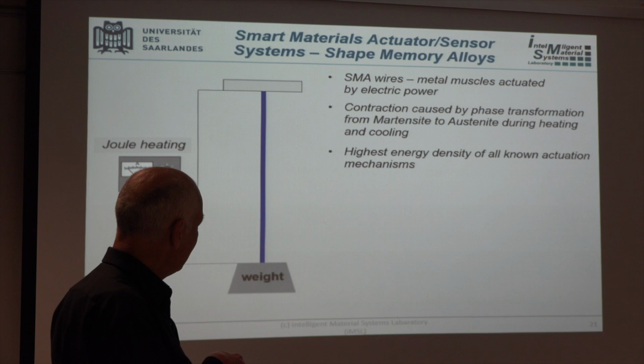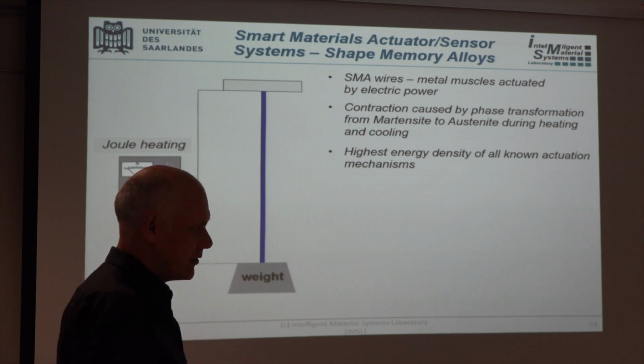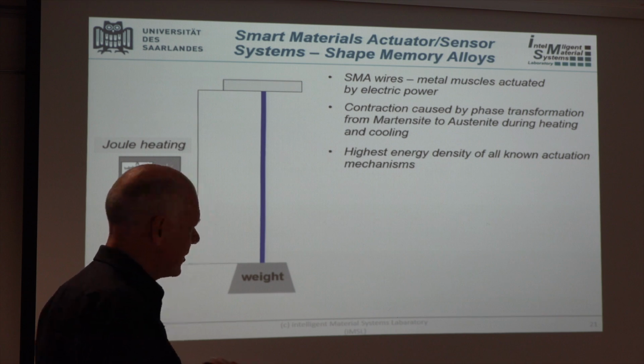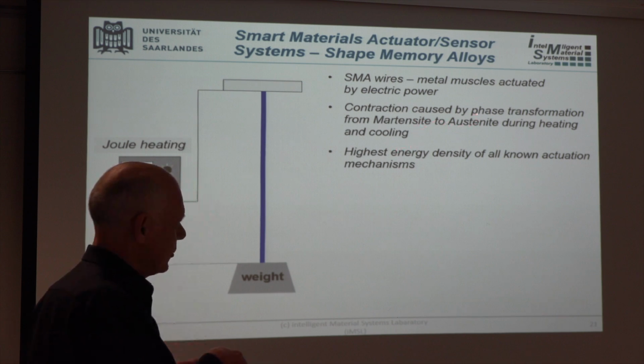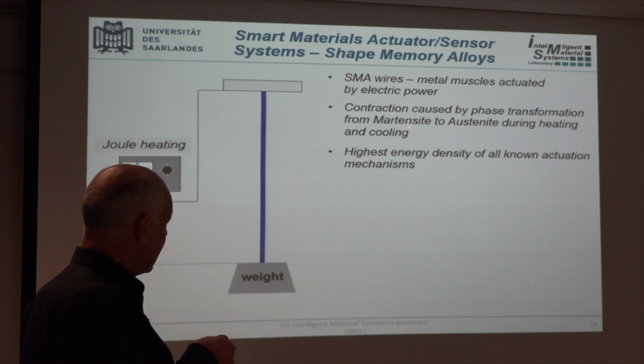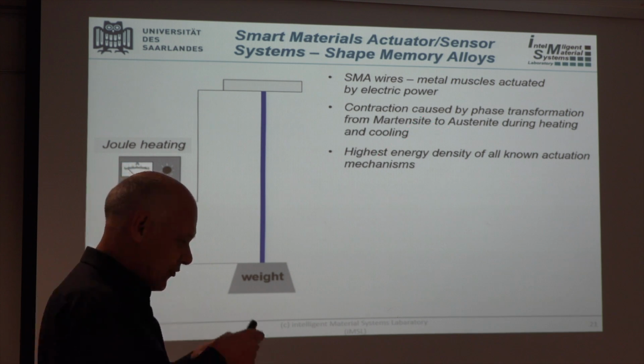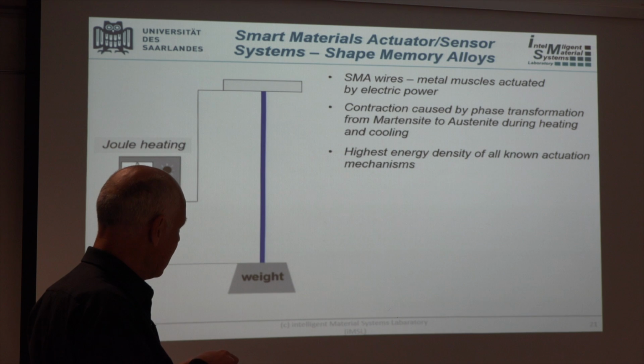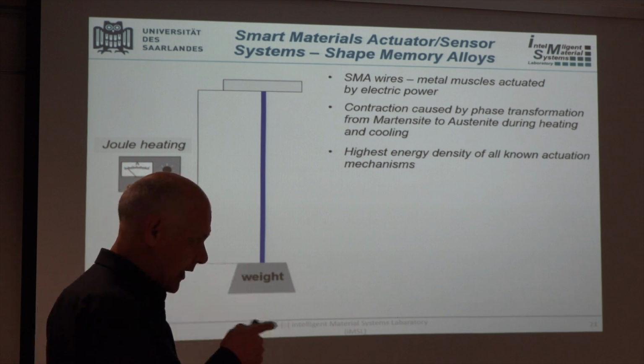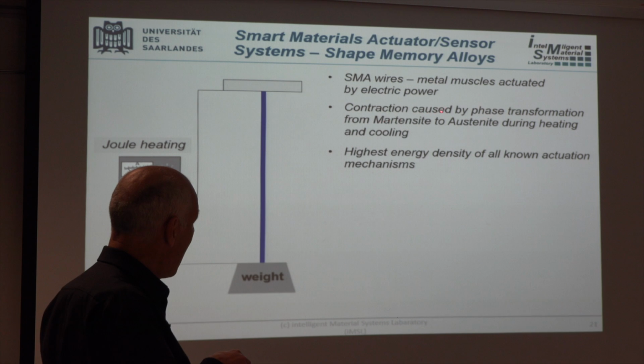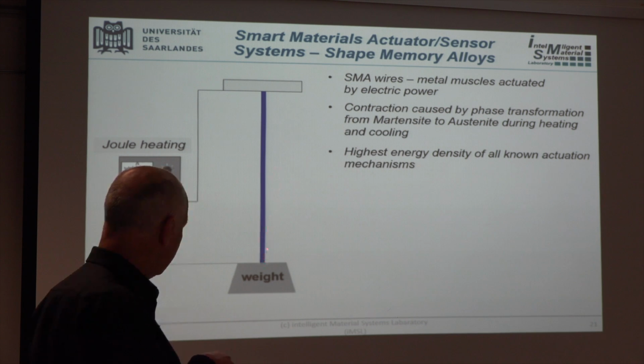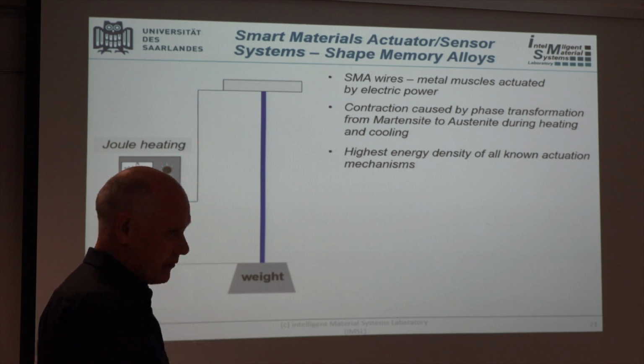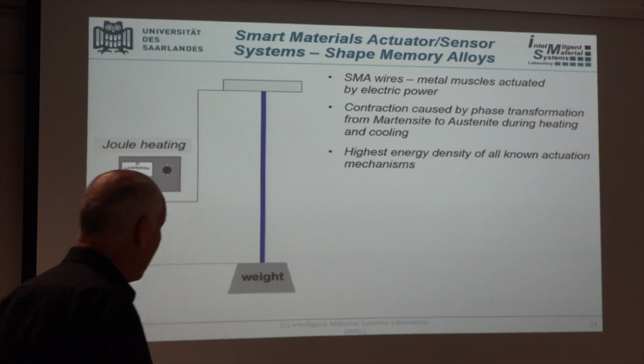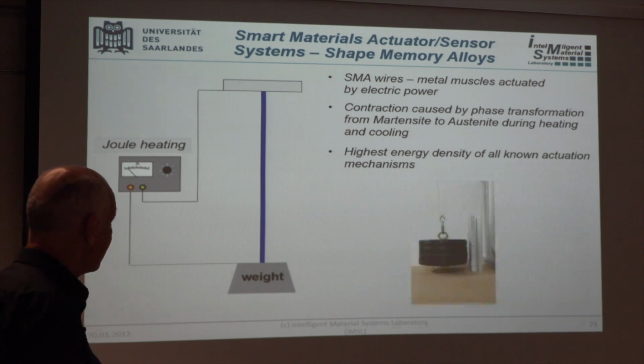And this phase transformation changes the crystal lattice structure from what's called martensite to austenite. You might have heard that in material science classes. That's very familiar also in steels. And it's that change from austenite, which has a shorter crystal lattice, to martensite, which is longer, and back and forth, which allows you to actuate the wire. When you contract, it changes into the short austenite at high temperature. And when you switch the current off, it cools off again, and then the weight restores the original shape.